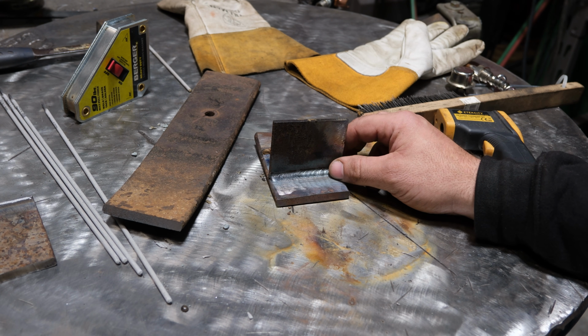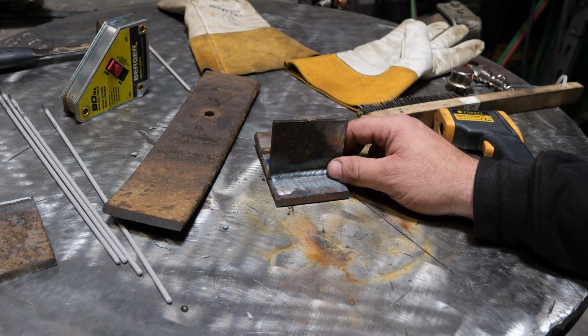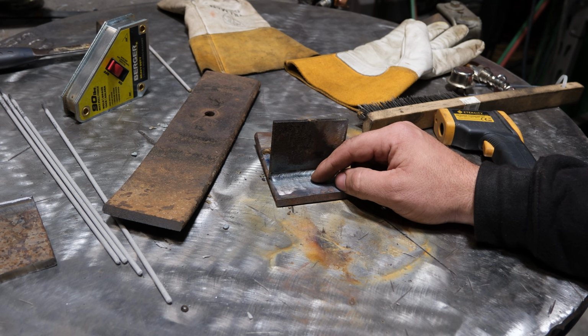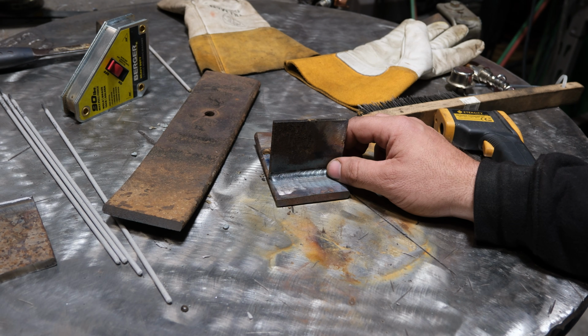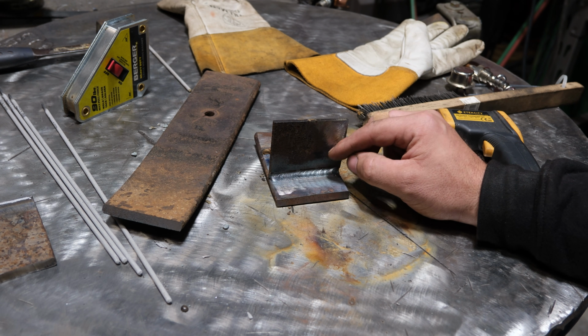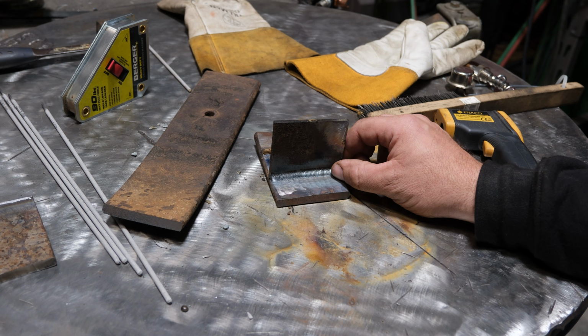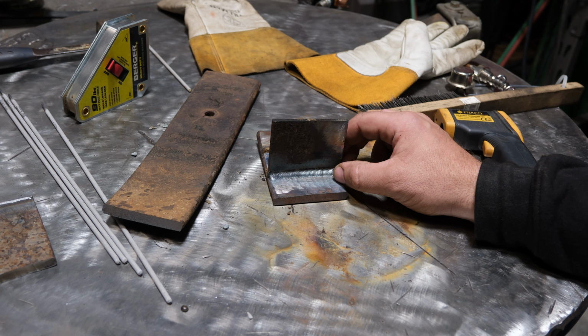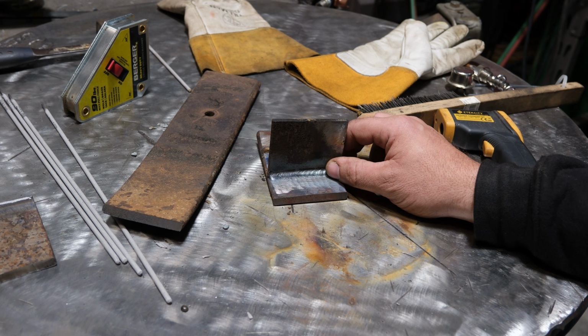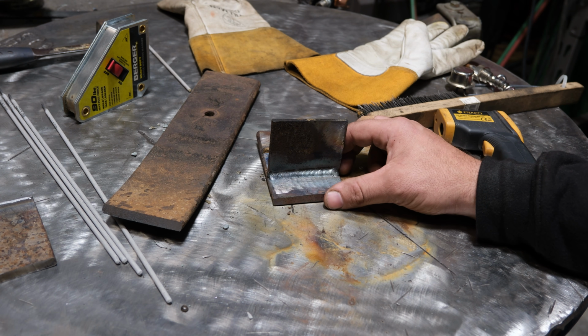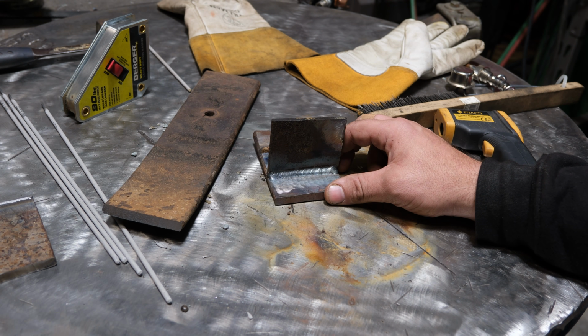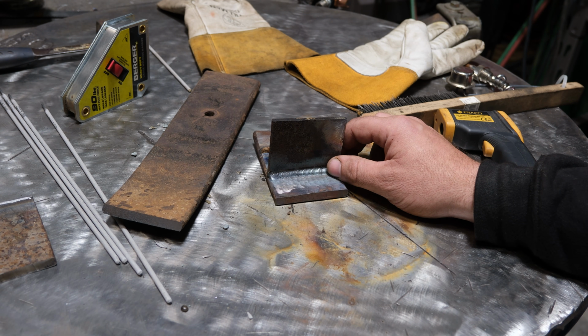In my actual hands-on experience doing this and repairing stuff for on-trail leaf spring failures, I have not had one fail after welding it. Arguably, this should have been welded with 312 stainless or some kind of alloy similar to that, simply because the carbon that would be absorbed from the base material wouldn't make the weld overly hard. But as you can see, even normal 7018 is perfectly okay to weld this stuff and get a reasonable result.